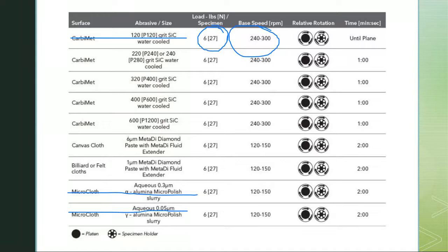The purpose of not using high RPM is, what do you think happens to the sample if you're trying to grind and polish at 800 to 1,000 RPM? For one, the chance that that sample flies out of your hand and hits somebody is very high. You do not know how the wheel is going to behave if you're also applying a load to that wheel. And second, third, fourth, fifth, it doesn't matter, you burn your sample. You overheat it. You cause mechanical deformation, and you're not really preparing your sample appropriately.